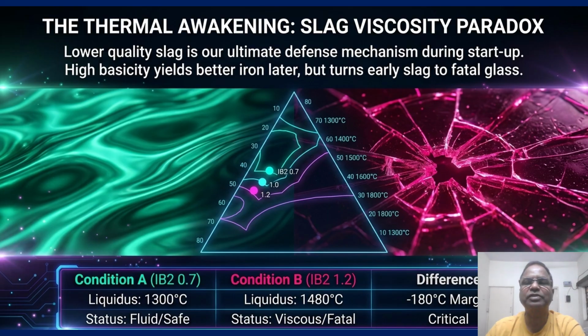Now at startup, lower basicity slag is safer always. This we have to keep in memory during revival of the furnace from blow-in. Lower basicity slag is safer because it stays more fluid at low temperature. If we push for high quality slag too early, we risk a freezing situation, and our system may be hampered badly. Our revival time may also be prolonged.